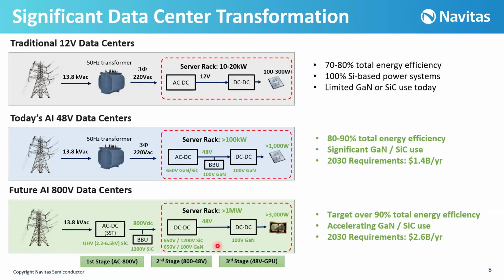And then again, by DC-DC converter using 100V GaN, we are powering the components, CPUs and GPUs with 3,000 watts, 3 times higher than the previous one that we are using today. By this architecture, we are able to increase the total energy efficiency more than 90% by accelerating the gallium nitride and silicon carbide usage. And the market requirement by 2030 is $2.6 billion per year.